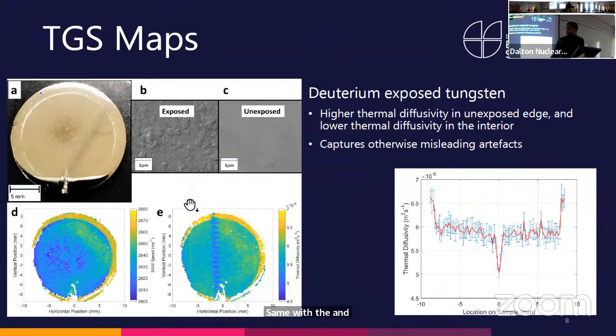And so initially when I measured the samples, we measured a line across the sample, just a line. And in the line, we saw this massive dip in the center. And for months, we were trying to think, okay, what's causing this? Is it something to do with the implantation and so on? But it was only when we did these 2D maps that we found these spots of low thermal diffusivity across the sample.